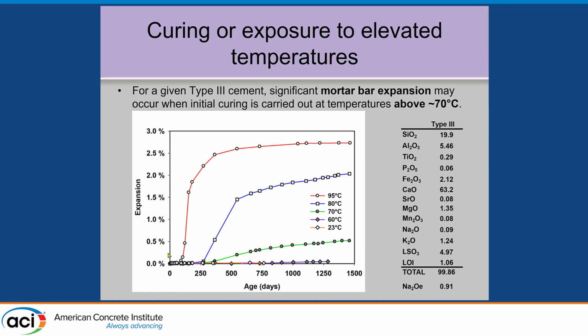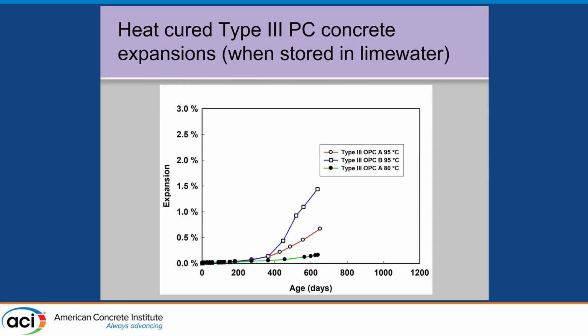So these are mortar bars. So 0.1 for mortar bars. And then you see as the temperature goes up, that expansion occurs earlier and gets bigger. And so that was the problem, that some of these heat curing regimes were going to very high temperatures, intentionally or unintentionally, to accelerate the curing to get the early strength. Typically for precast products, they're trying to get that early strength. So these were just heat cured for several hours at those temperatures and then placed in water, and they expanded over time. And then we also did some work with concrete.